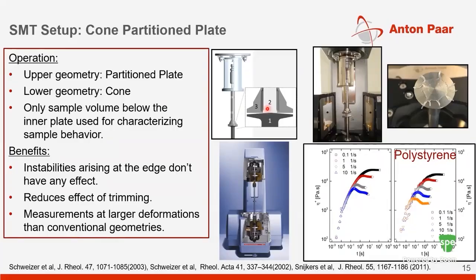This has advantages, as you can see in the image on the right here. Even though edge fracture has happened, and as we saw earlier, the fracture propagates inwards, you can see that even though the fracture started from the outside periphery, the sample inside where the measurement is happening is still intact.